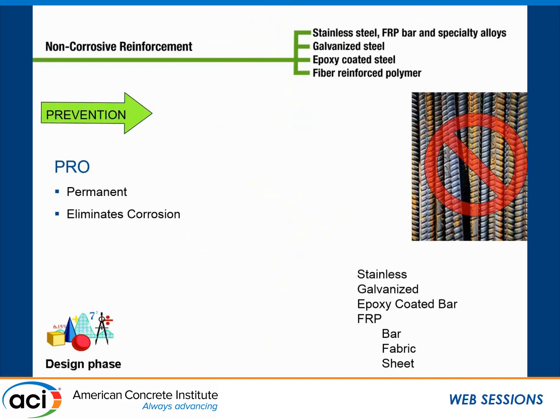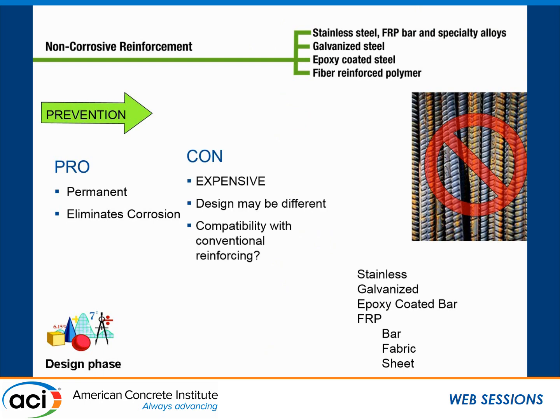Non-corrosive reinforcement. It's really great. It's permanent. It eliminates corrosion. Unfortunately, it costs a lot. Design may be different. It may develop differently, may have different yield strengths. Is it compatible with conventional reinforcing? You get too noble, like try put carbon fiber in contact with steel, it's going to cause the steel to corrode. What about if I'm using epoxy-coated rebar and I've got pinholes or voids? What about the bond that forms on galvanized rebar? I've got a corrosion product that develops, and that's going to change the way it bonds to the steel.